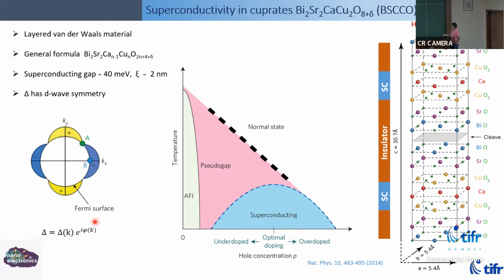This phenomenology I already explained. There is a superconducting dome: as you tune delta in the copper oxygen planes, it will change TC. This brings me to one of the challenges of working with this variety of high TC superconductor, BISCO. The oxygen wants to leak out of these copper oxygen layers, and it will quickly degrade into a material which does not have the same TC as when you started the experiments.